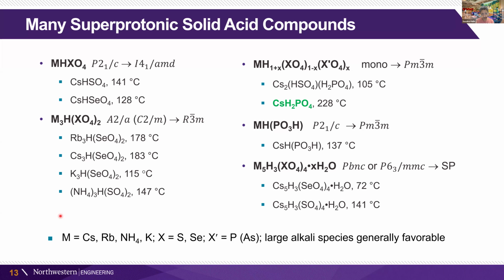This is just the whole range of them. There are ones that go from a monoclinic structure to a tetragonal structure, ones that go from monoclinic to trigonal, from monoclinic to the cubic, which I described to you. That's the cesium dihydrogen phosphate. Monoclinic to another trigonal, where on that fourth example, the polyanion group actually has a hydride ion replacing one of the oxygen ions, so unusual chemistry, but again goes to a cubic high conductivity phase.